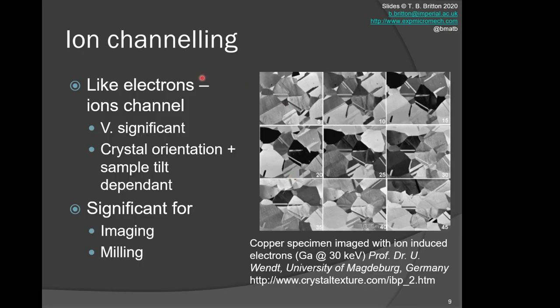Ion channeling is important, similar to electron channeling. The idea I use is that if you're looking at a vineyard with very well-planted vines at equal spacing, if you look down the rows, you can see very far. If you tilt slightly off angle, you see less far. The same thing happens in a crystalline lattice. This is hugely significant within the FIB. Here are a series of images of ion-induced secondary electrons. As we rotate the sample with respect to the primary probe, we can see strong orientation dependence when looking at copper. For instance, we see the twins and other grain orientations revealed beautifully in these micrographs.